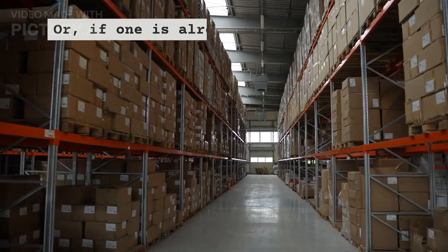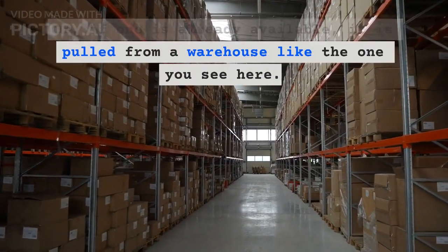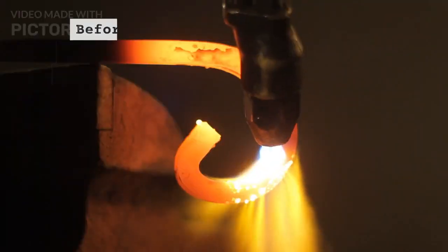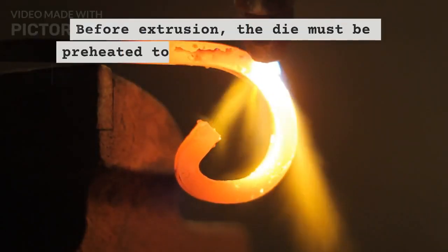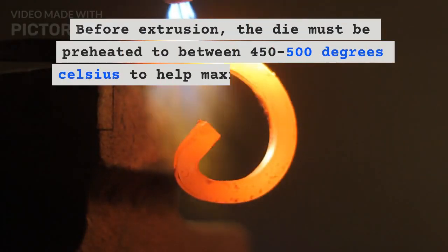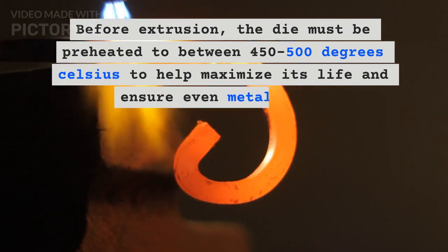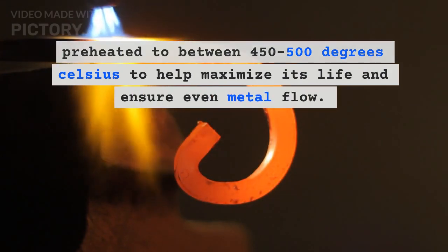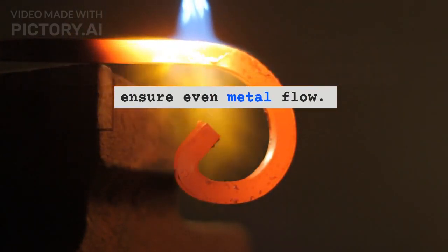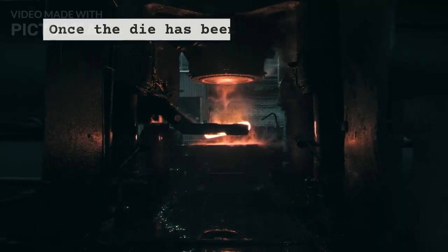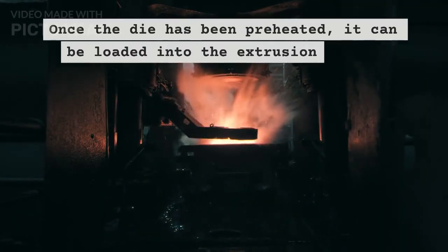Or, if one is already available, it is pulled from a warehouse like the one you see here. Before extrusion, the die must be preheated to between 450 to 500 degrees Celsius to help maximize its life and ensure even metal flow. Once the die has been preheated, it can be loaded into the extrusion press.